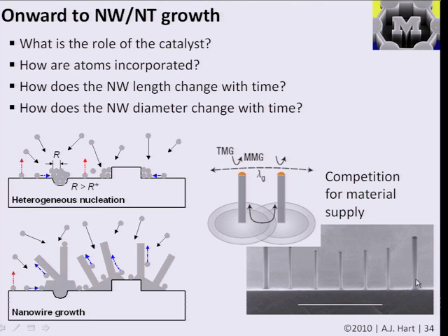So in this case, you can see we have two big particles on both sides, and because there's more surface area available for precursor to deposit on this wire, it can grow taller, and also it can provide more supply to the neighboring wire by this minority path of diffusion up the surface. So these kinds of exchanges, by the principle of relative sizes, sinking or sourcing certain amounts of material, are very important for practically governing the size distributions of structures that we might make.